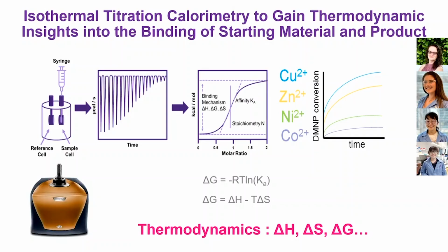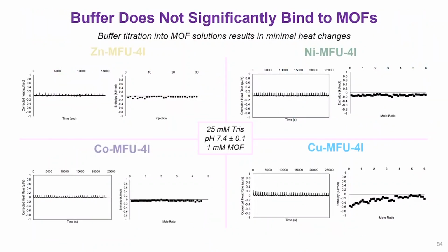Using this technique, we could get delta H, delta S without any assumption. Experimentally, we could extract it. These techniques are used by biologists all the time in order to understand the active site and the binding energy of substrate to the active site of the enzyme and the protein, especially in the pharma industry, to see if a drug binds to the active site or not. But also, when you do this kind of titration, you want to make sure the background is not getting involved, and that's what you see. We want to make sure our buffer, our water, everything is not interfering.